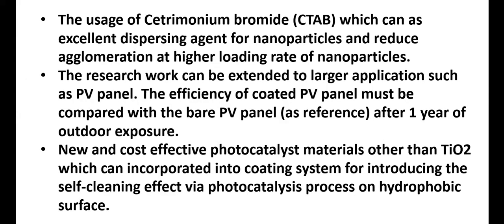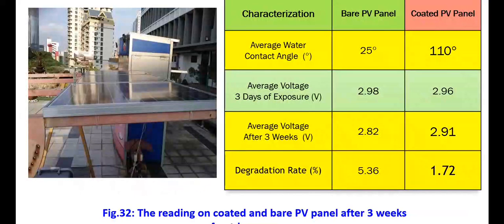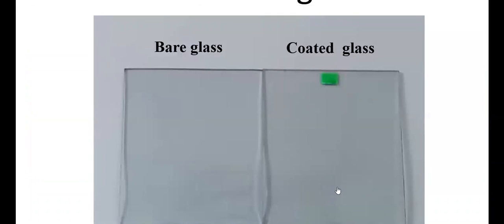Okay, so these are our photovoltaic panels, where we have also spray coated our photovoltaic panel, and the coated panel shows a degradation rate of 1.72 after 3 weeks in service. And for a bare panel, non-coated panel, it shows a degradation rate of 5.36. Okay, this is our self-cleaning test. I want you to see the video.